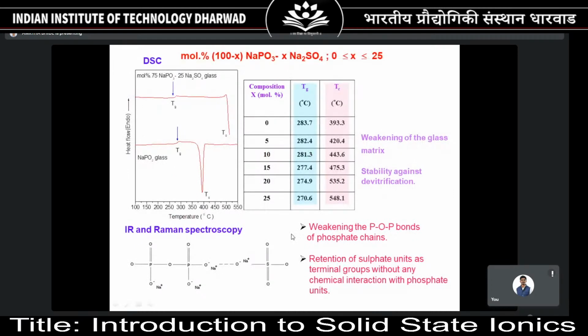These are the characteristic features when you have different weight percent or mole percent of sodium sulfate: the glass transition temperature has decreased. As I told, glass transition temperature is a significant characteristic feature of a glass. If Tg has decreased, it means the glass matrix has become weaker. That means you have a lot of open space where the ion can hop from one location to another. Whenever you have such glasses, people have studied by means of infrared spectroscopy and Raman spectroscopy how the bonding is changing in the case of dopants, or in a simple glassy electrolyte.